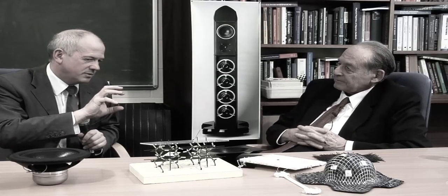So these molecules that are attached to the carbon molecules, is it these molecules that move when it's subjected to the sand, or are all the molecules moving? All the molecules are moving around, yes. It's when it's going from the glass to a rubber, when it's going from an elastic solid to a viscous liquid, if you like. It's not there yet, but it's doing that. And that's why it's a viscoelastic relaxation process. Is this what I've read somewhere, where it's moving from a glass phase to a rubber transition phase? Yes, it's called a glass rubber transition, Tg. And it just so happens that it's around room temperature for polypropylene. It suits your purposes. Interesting. But it doesn't melt, of course, until you get up to 130, whatever, 190, whatever. So you've got a high temperature melting point.